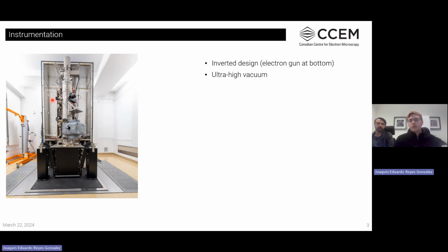You also have an ultra-high vacuum instrument, so this is an order of magnitude higher vacuum than is typically encountered in TEMs. This helps with keeping the system clean, with reducing contamination throughout the entire scope. It means that there's going to be some greater considerations for prepping your samples, putting your samples into the scope, and with working with it. There's a little bit of more learning required in that aspect.